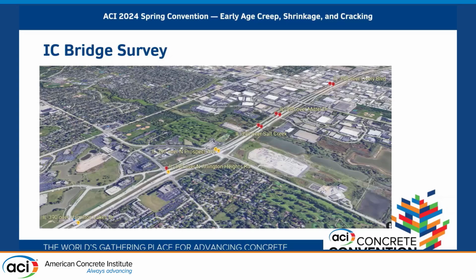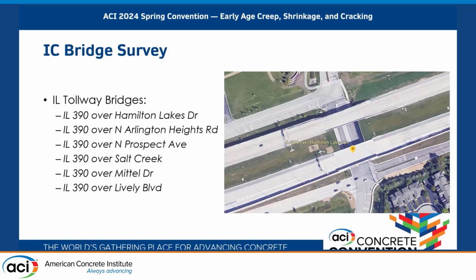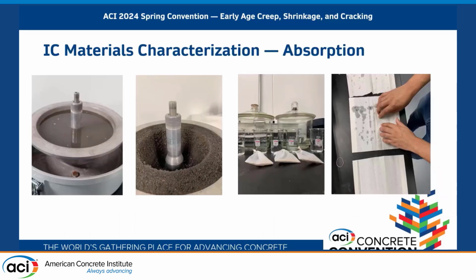Part of the project also included a survey of bridges in the Illinois Tollway that have used internal curing in their concrete mixtures. There were 6 bridges that were surveyed. Obviously, this is not the focus of the investigation, but in general, the condition of those bridge decks, compared to other similar bridge decks in the same tollway system, exposed to the same environmental conditions and same maintenance operations, was found to be in much better shape than bridges that were not built with internal curing. So again, we're not reinventing the wheel here, it's just reassuring and demonstrating that the technology, when applied or implemented adequately, is actually useful.